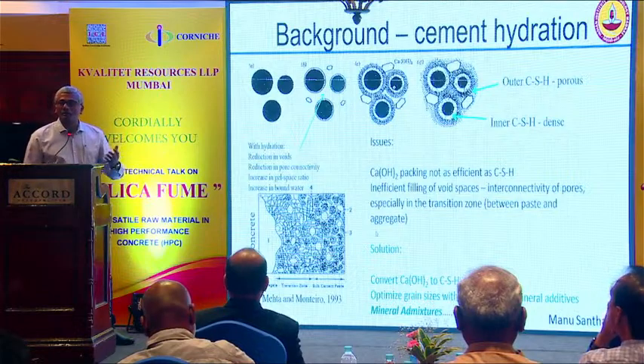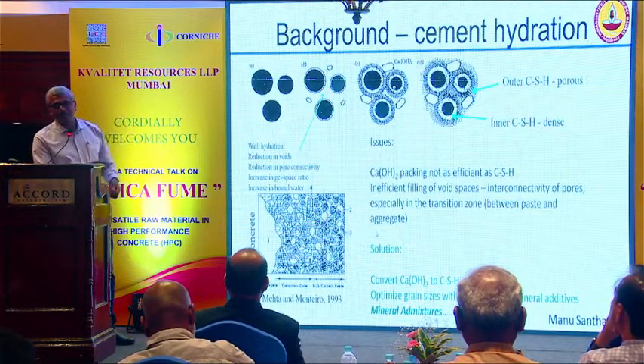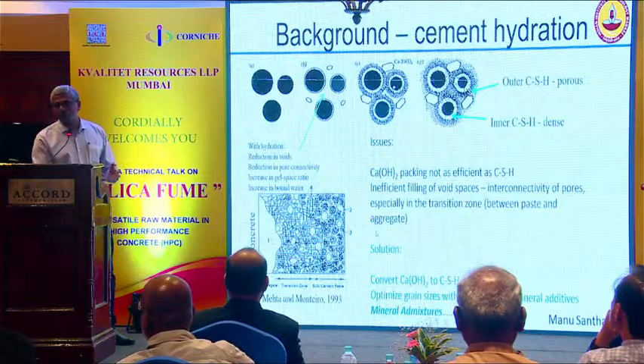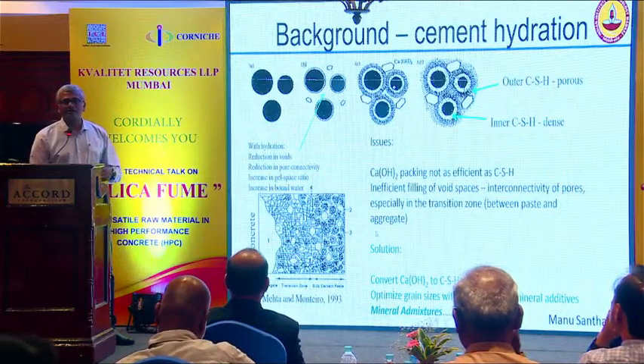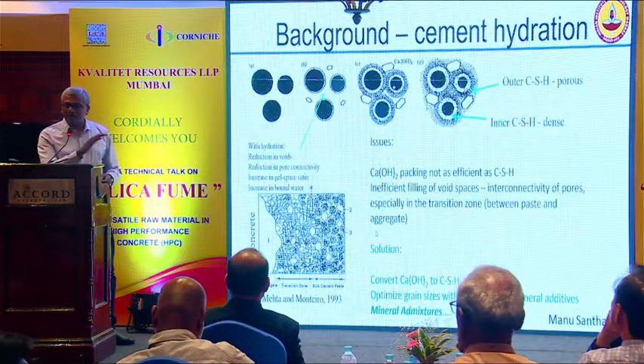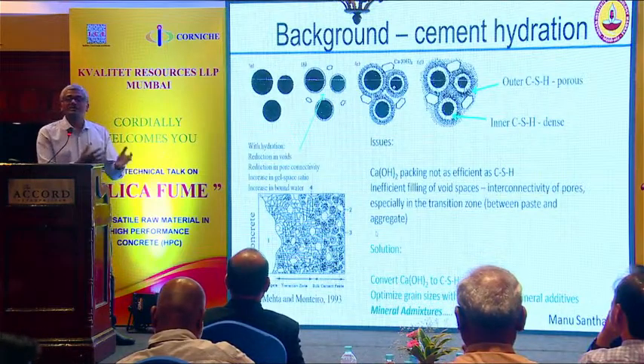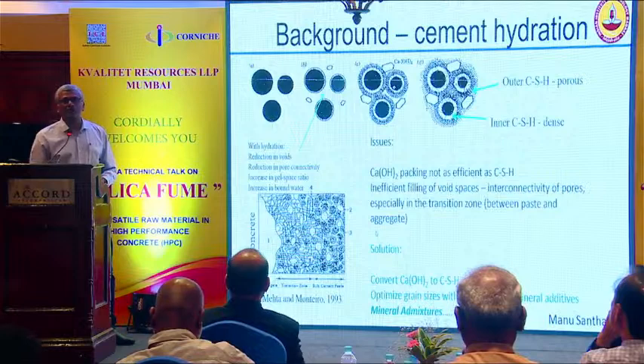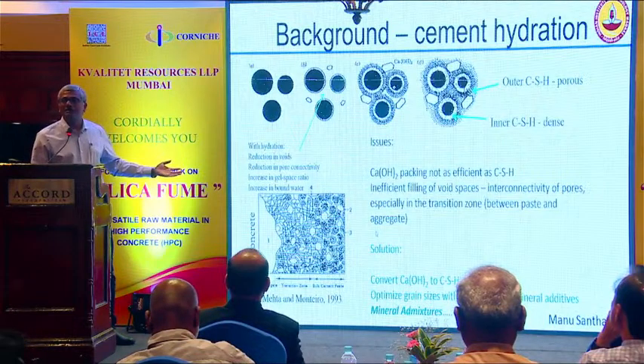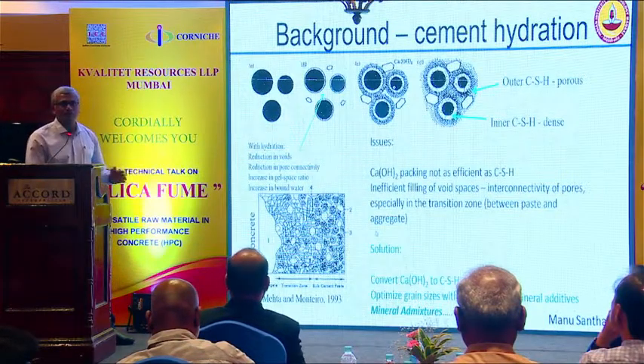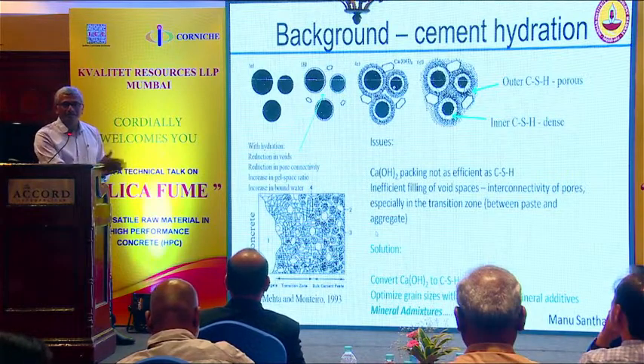If you have tested concrete, you'll know that when you fail the concrete, the cracks go around the aggregate for most normal grade concretes, right? Unless you go for high strength concrete, where the cracks go right through the aggregate. Normal grade concrete, the cracks go around. So to strengthen the interface and to ensure that you get a stronger concrete, you can densify the interfacial zone. So as you become stronger and stronger, the cracks will tend to pass right through the aggregate.